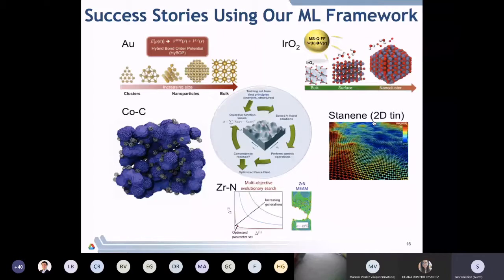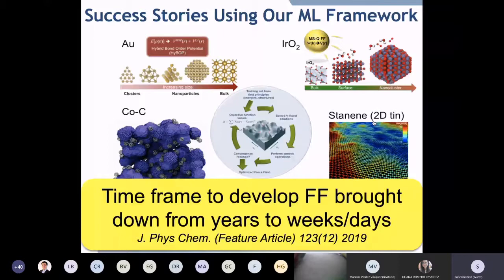We've looked at 2D materials such as stanene, a material that was actually discovered like 3 years back, and we were able to come up with the potential within 6 months of its discovery. Zirconium nitride, a nitride system for which we used a multi-objective search. Cobalt carbon, a heterostructure system, for which we looked at modeling the interactions with a single framework. Essentially what we have done is brought down this time frame for force field development from several years down to weeks or days. So that is an important advancement in model development that has happened recently.